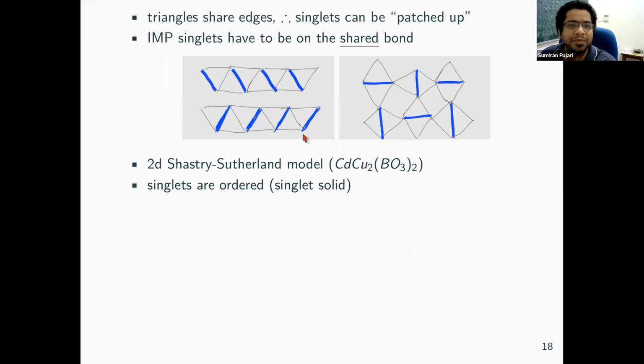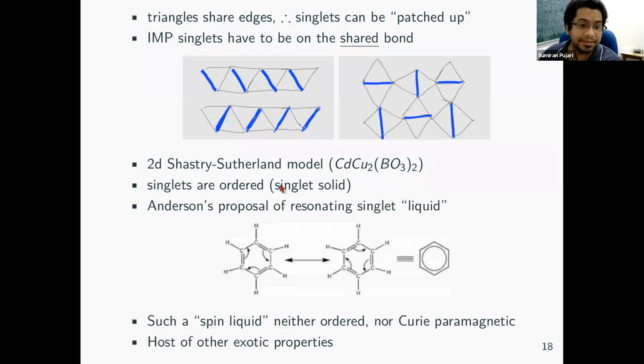So this Majumdar-Ghosh model works in 1 dimension, and there is a similar model in 2 dimensions called the Shastry-Sutherland model, which has a potential material realization in this material, where also the singlets can themselves order. So you can think of them as a singlet solid as opposed to the Néel state, which was the up-down state. So a singlet solid, note, will not have any net magnetization because each singlet is up-down minus down-up. So it does not contribute any net magnetization. So this is a non-magnetic, but a periodically arranged state of singlets.